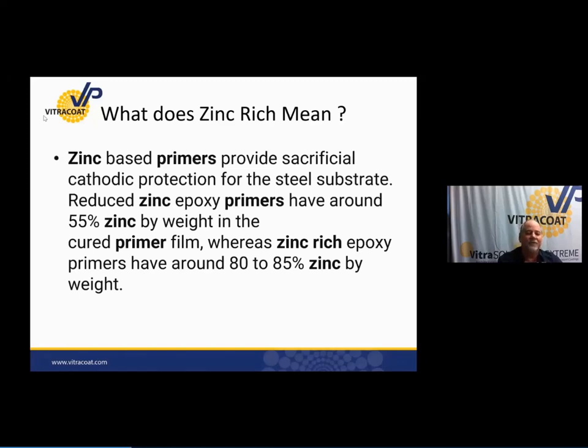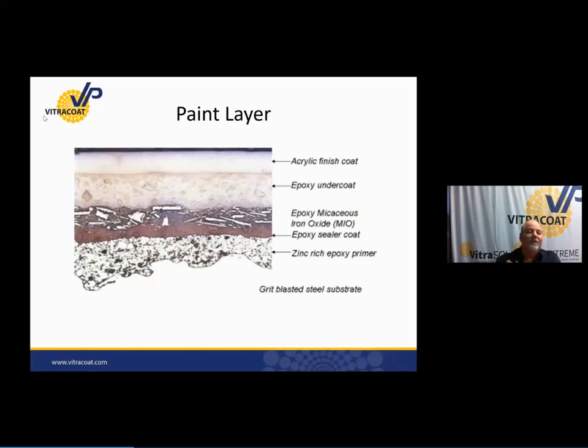You have to have enough zinc. I've seen zinc primers that have 13% zinc. The hard reality is all you're doing is spraying a very heavily weighted powder with very, very little benefit from the zinc itself. You might be better off just using an epoxy. This is what it looks like. If I take a side cut from the coating in layers, look at the zinc-rich primer at the bottom. It has so much zinc that the zinc itself is going all the way through to the steel surface itself. In this case, a grit blasted surface. That's when you get the benefit of the zinc within the coating itself.